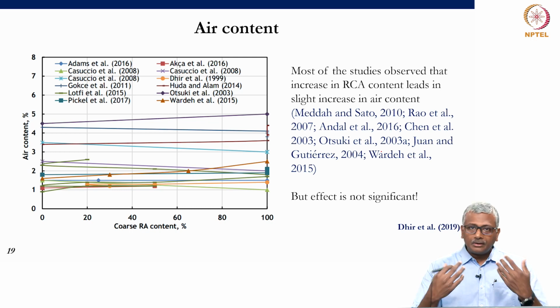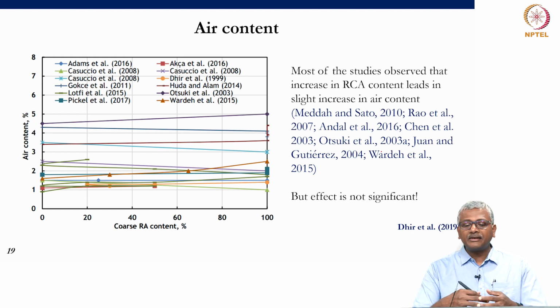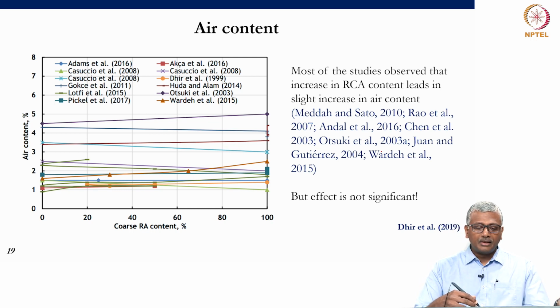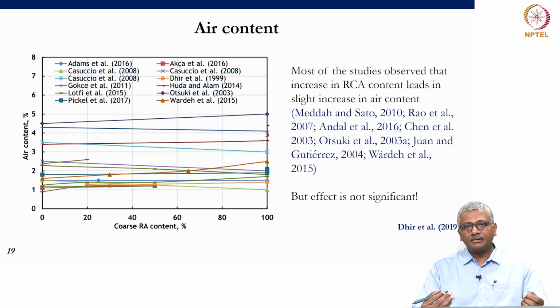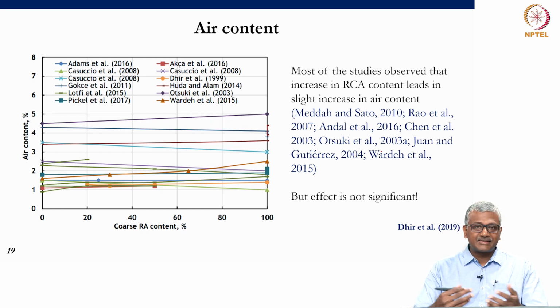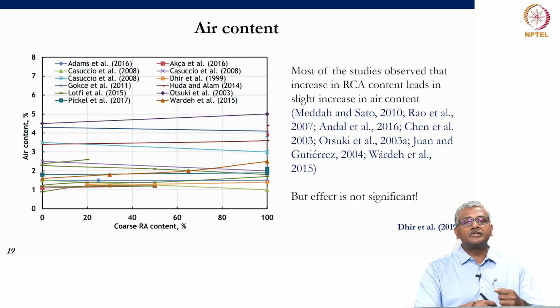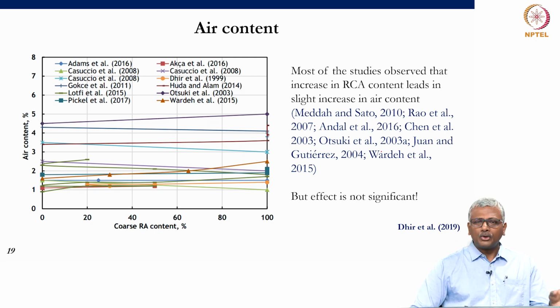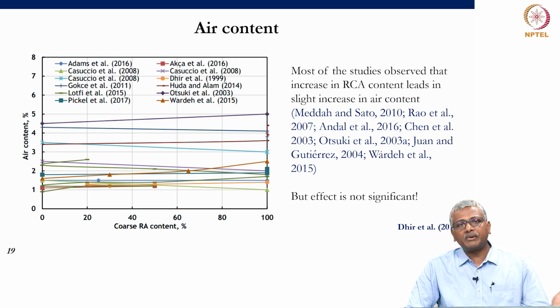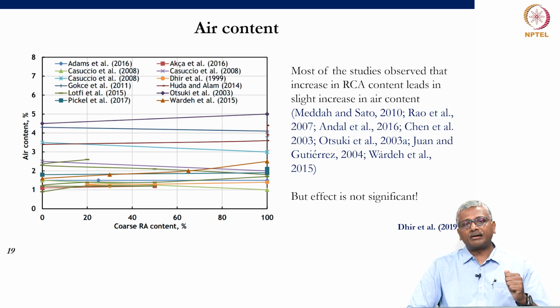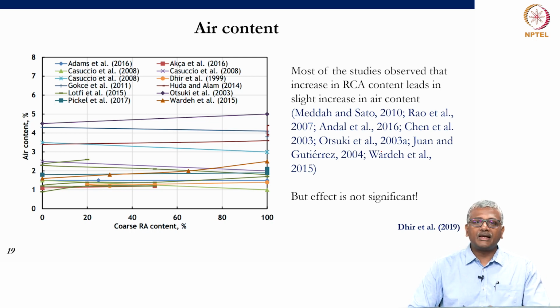Again, air content, you have more fissures and cracks and pores present in the adhered mortar, and because of which you can see a minor increase in the air content of the concrete with respect to conventional aggregate. Okay. And you can see from this data that the effect is not really significant, right. You can see some increase, but it is not really that significant. As long as you are designing air entrained concrete with proper distribution of air bubbles caused by the presence of the air entraining admixture, you do not really need to worry too much about the fact that you are replacing conventional aggregate with recycled concrete aggregate. It is not going to totally throw away your result of the air content too much.